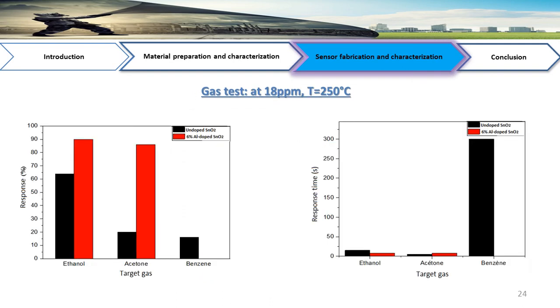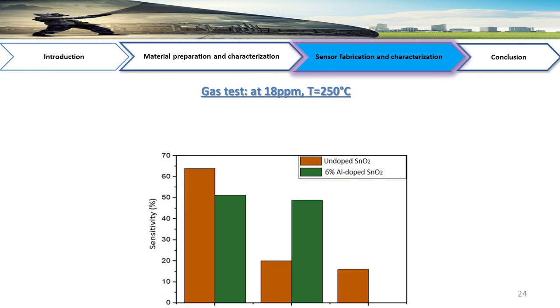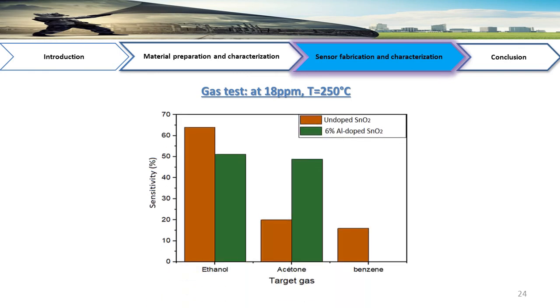To improve the characteristics, we increased the activation temperature to 250 degrees. We observe that there is an improvement in the response and the response time of our sensors by temperature effect, and that the sensor based on undoped tin oxide microtubes has a high sensitivity to ethanol compared to the doped sensor, and the doped sensor has a low sensitivity to benzene.